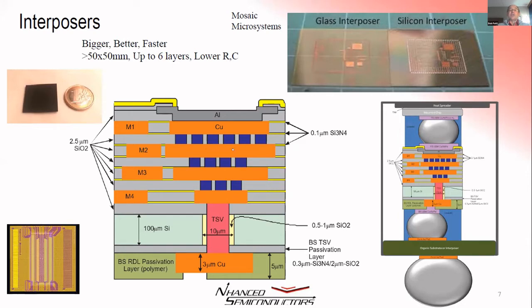An area that we're starting to do some new and interesting devices in is glass interposers. We work with Mosaic in this area. And, you know, as a glass interposer, it has much lower capacitive coupling. It's very good for RF. And another unique aspect is that we can put waveguides into it to build photonic mixed with electrical circuitry onto a piece of glass that is perhaps 50 to 60 millimeters on the side at its maximum.